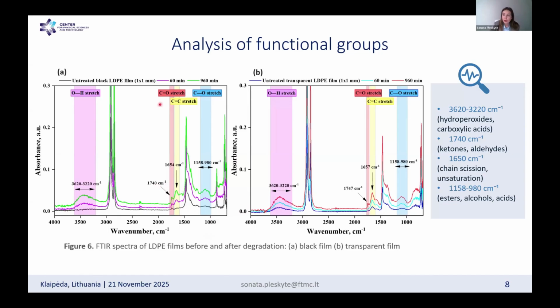Especially the carbonyl group is the main indicator for the successful oxidation process within the polymer chain. And of course, we can also see the formation at 1,654 inverse centimeters, which is attributed to carbon double bond carbon stretching, and this most likely occurs due to the main chain scission of the polymer. And of course there is some more branching over here, but I would like to talk a little bit more about the trends and similarities that we found in transparent LDPE films.